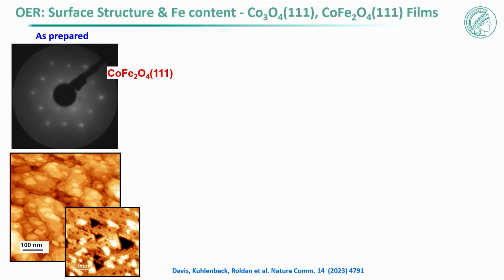So when I do this, this is, for example, a cobalt iron oxide system that I made, a thin film, just the same orientation. And this is as prepared material. These are scanning tunneling microscopy images. These are atoms. You see defects, so these thin films are not perfect, but this reality is like this. Nature is not perfect either.